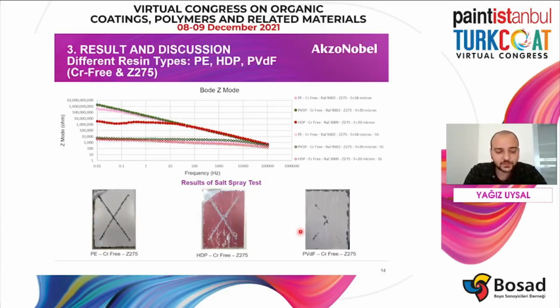And here we can see the pictures of the panels after the accelerated test. And moreover, electrochemical impedance spectroscopy measurements are obtained again after the accelerated test. In the graphs, the circle ones correspond to the measurements before the accelerated test, and the diamond ones correspond to the panel measurements after the accelerated test. If we look at the Bode impedance values, it can be seen that the PVDF coating has the highest impedance value and the better linear decreasing, which we can simulate in the accelerated test. PVDF coating has the least amount of blister and rust formation.